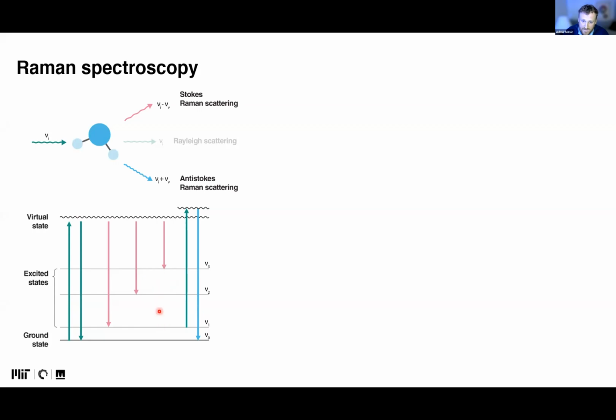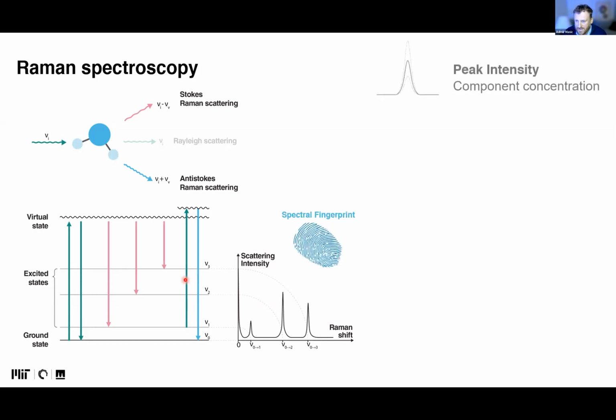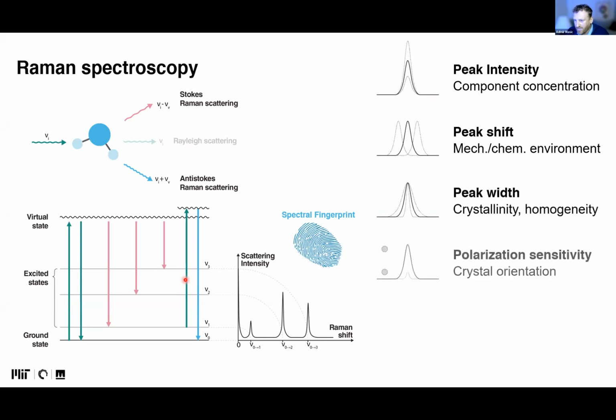These shifts, these differences in light energy, will give us a fingerprint for each of the materials that we investigate using this tool. That fingerprint carries a lot of interesting information that is very local around that vibrational unit. It's molecular information, short-range order interactions that are evidenced in these spectra: peak intensity, peak shift, peak width, polarization sensitivity. All these details about the peaks will inform us about the unit that is vibrating.